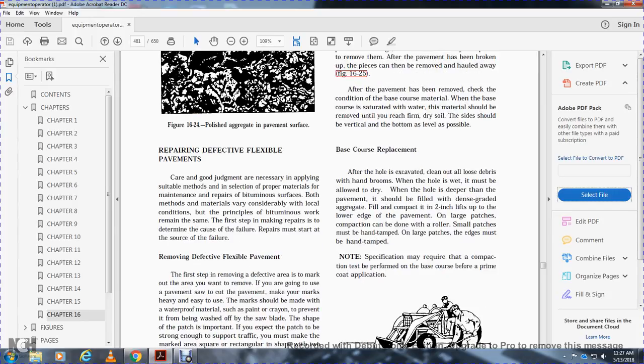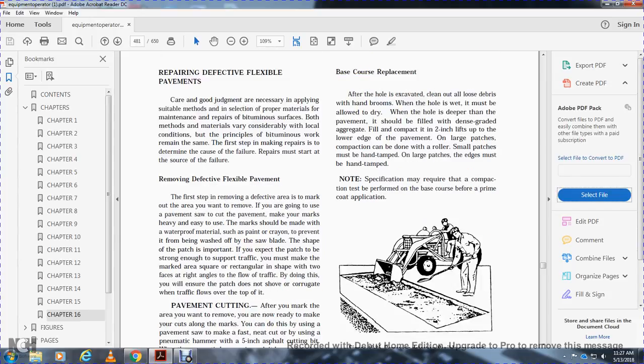Base course replacement. Excavate the hole and clean out loose debris with a hand broom. When the hole is wet, it must be allowed to dry. When the hole is deeper than the pavement thickness, it should be filled with dense-graded gravel, compacted in 2-inch lifts up to the lower edge of the pavement. For large patches, compaction can be done with a roller. Small patches must be hand-tamped. The edges must also be hand-tamped. Specifications may require a compaction test performed on the base course before the prime coat is applied.